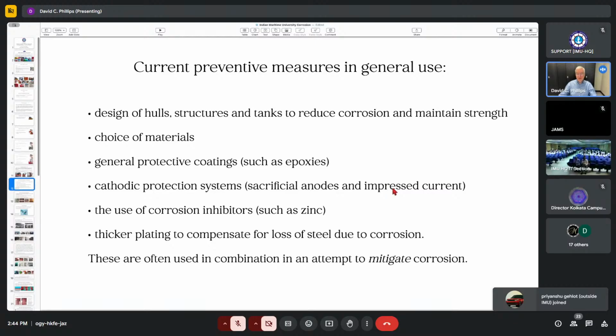And there's also another system whereby an electrical current is put into cathodes on the hull of the ship. It's designed to prevent the electrical currents which flow around the hull from affecting the main hull. They tend to be attracted to or affect the impressed current terminal. So this is another method that's used, and it's designed to reduce the effect of corrosion. There are corrosion inhibitors. Zinc is quite common, and they're put on as part of the protective coating, and they're designed to stop the corrosion from happening or at least slow it down. Another approach is to use thicker plating. In other words, you compensate when you design your ship by adding however many millimeters of steel everywhere to compensate for the expected loss of steel due to corrosion.